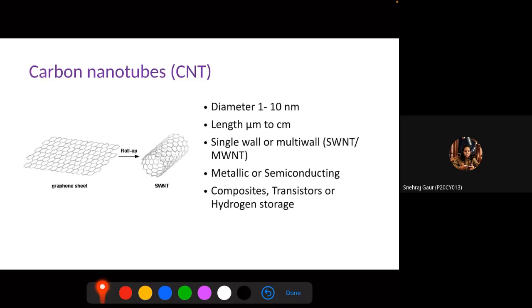You take normally these carbon electrodes, and you apply a high voltage across it, so you have a high voltage discharge, and you do it normally in an inert atmosphere, either helium or argon, and you get these different nanostructures. So mostly, not graphene, but you get fullerene, you get these carbon nanotubes. Just by taking the carbon electrode and applying a high voltage discharge, you get this.